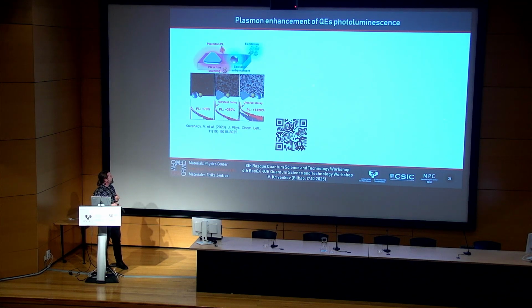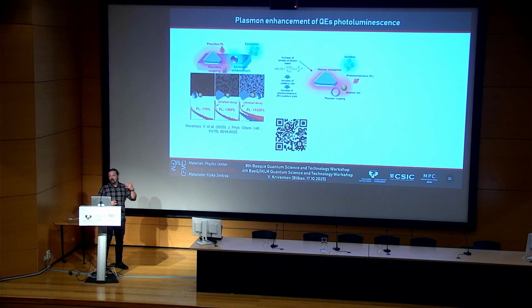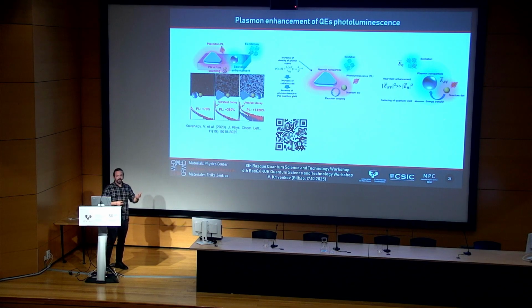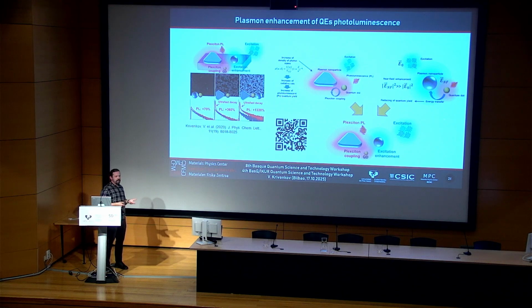So we performed the coupling of quantum dots with different types of plasmonic cavities. We could achieve the Purcell effect, which means the compression of the emission lifetime, the shortening of T1 for quantum dots. We also could achieve an increase of the emission intensity by the coupling of the excitation field with plasmonic cavities, leading to an increase of the photon flow from our quantum emitters. And we could combine these effects to achieve both compression of the lifetime and an increase of the photon flow. In our case, it was more than 13 times.